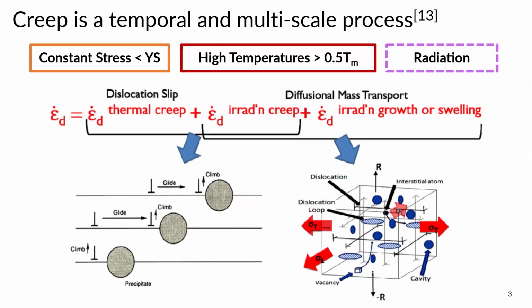Creep is a permanent deformation mechanism in which a combination of high temperature, high stress, and radiation can accelerate the rate at which your material will permanently deform. And so you can see in red, there's the strain equation, which is a superposition of all of these different functions. So you have strain components from your temperature and your irradiation. And so if you take irradiation out of the equation, your material is going to be strained just from the high temperature, which you can see the first component is your thermal creep strain contribution. And when you introduce radiation, it just makes things worse.